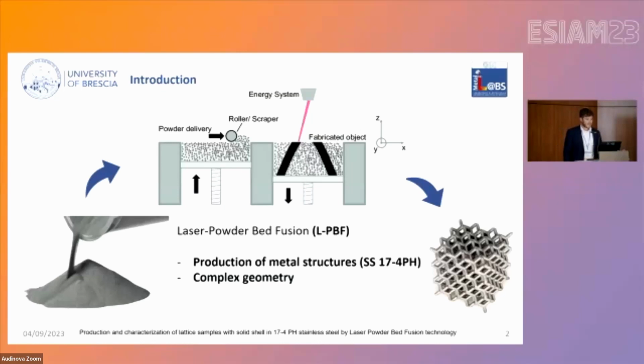a laser, that melts the powder locally and layer by layer fabricates the 3D component, as you know. In this case, for the production of the metal structure, we decided to use the stainless steel 17-4 PH, for its good weldability, for its excellent corrosion resistance, for the microstructure characterized by austenite and martensite, and also for the combination of high tensile strength and high toughness. This kind of technology is also perfect to build complex geometries such as lattice structures.